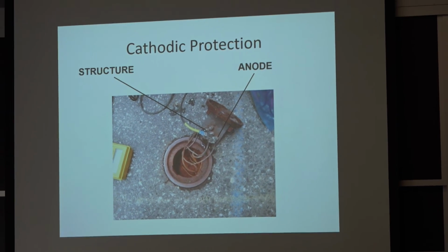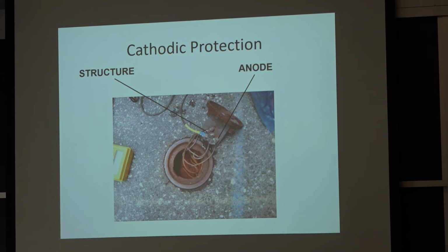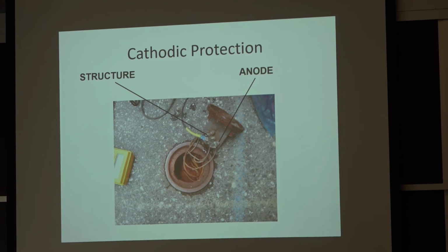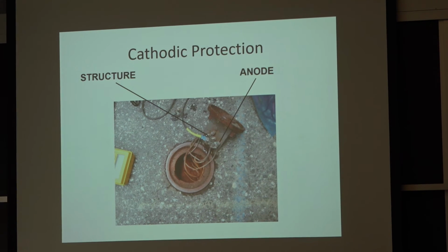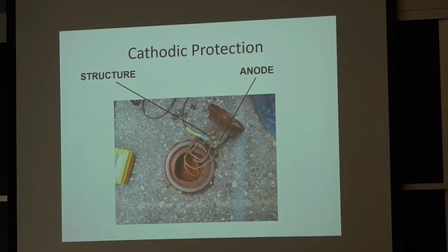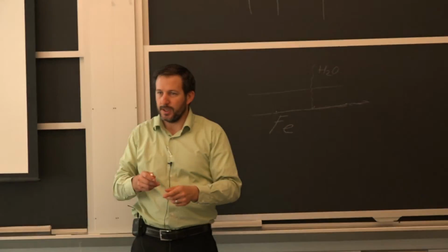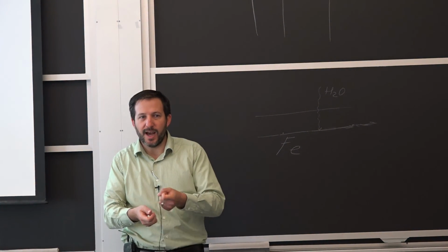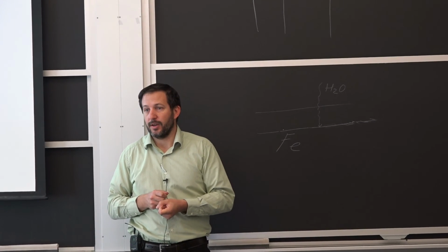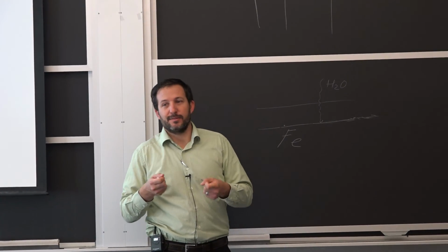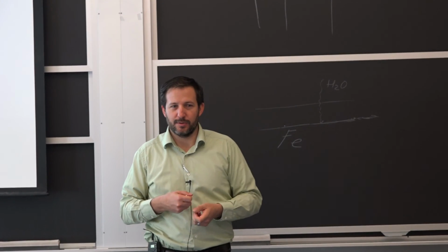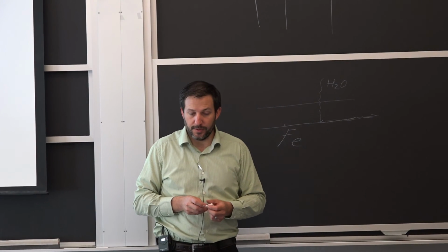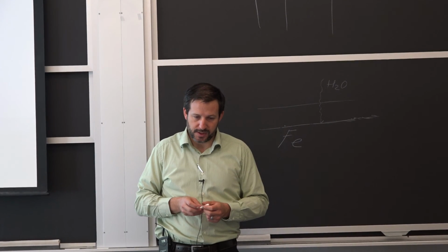This is something that when we talk about large utilities, pipings, and things that are in the ground, you can't access them after the fact, so you have these locations to control the sacrificial anode. So let's say I put some magnesium anode somewhere in the ground, I run the wire to this port, and then I can also connect it to the steel structure I'm trying to protect, so I can go back and verify if my system's working after a while. And then if it's not, then that's a little bit of a challenge to go and put some more anodes and all that. So it's not perfect, but when talking about large structures and you're trying to monitor them and you have the cathodic protection, that's a way to do it.